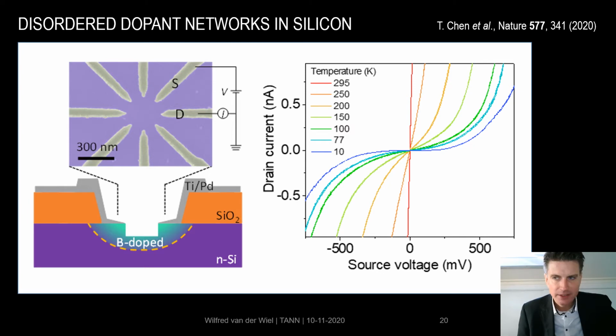A little bit more on the device. So here you see again a top view, the 8 electrodes and the central region. In order to arrive at a nonlinear system, we basically need to use now the physics of variable range hopping. This happens at relatively low dopant concentrations. So when we dope the central region, we have to etch down to arrive at a typical doping concentration of about 10 to the 17th per cubic centimeter, in which at lower temperature this variable range hopping regime occurs, as you can see here on the left. So basically up to around 150 Kelvin, you see that the IVs are very nonlinear, and we can use that nonlinearity for realizing our functionality.